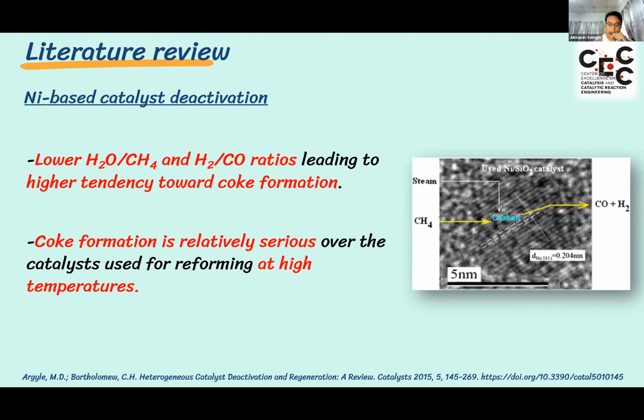The tendency toward carbon deposition depends on the atomic ratio of oxygen to carbon and the ratio of hydrogen to carbon. A lower water to methane ratio and hydrogen to carbon monoxide ratio lead to a higher tendency toward coke formation. And coke formation is relatively serious over catalysts used for reforming at high temperatures.